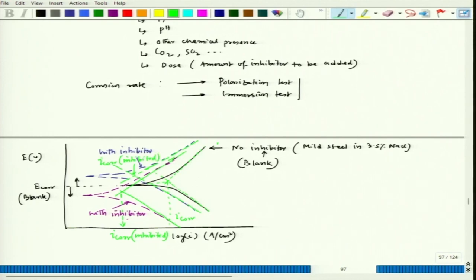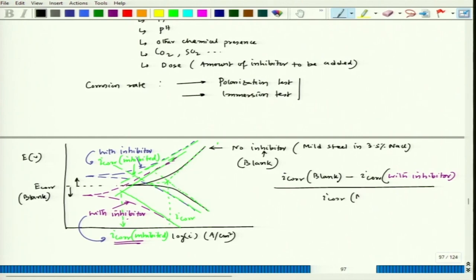Fine. Now, we can calculate the inhibition efficiency for both the cases. So, this is for this case and this is for this case. Now, we can do it like this. I corr blank minus I corr with inhibitor, so that means we are talking about this one, divided by I corr blank. So this is my inhibition efficiency in terms of percent. So I just multiply by 100. Okay. So that becomes my inhibition efficiency.